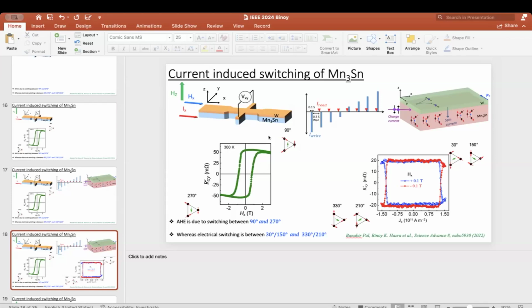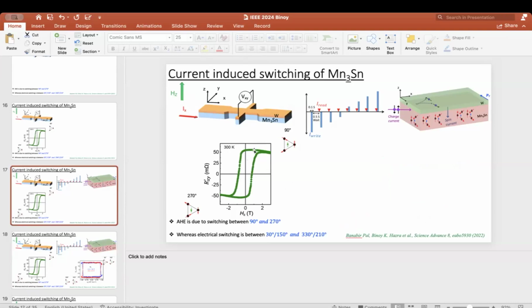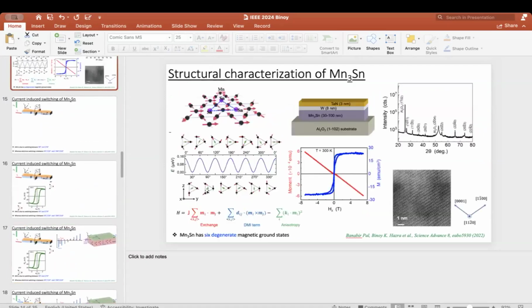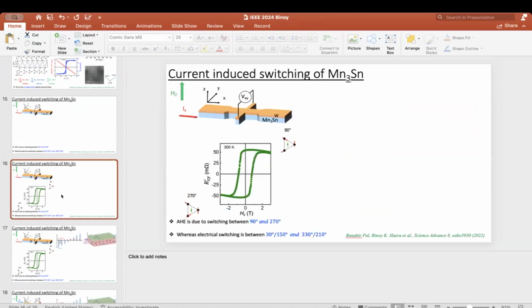Okay, thanks. Another question is: out of the 6 domain states, on what basis are you saying 90 and 270 are responsible, and the rest 4 are not? The basic understanding is, the Kagome plane is perpendicular here, right? The in-plane moment usually lies in the Kagome plane, so the small in-plane moment is along the z-axis. If you look at all the domain structures, the 6 domain structure, 30, 90, 150, 210, 270, 330, the small green arrows represent the net moment in each domain structure. Only 90 and 270 are along the z-axis, basically plus minus z-axis. So when we apply the external magnetic field, the maximum field-induced switching happens because of these 90 and 270. That is a reference point you can think.